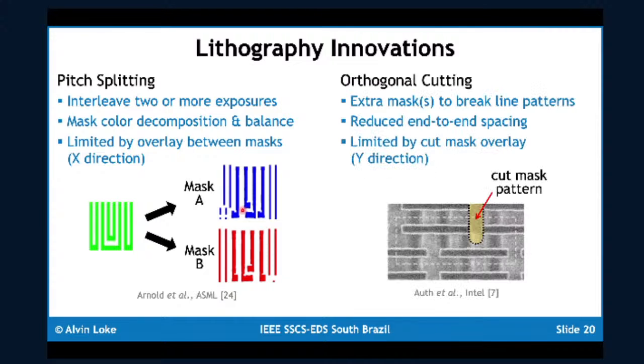Another approach is to use orthogonal cuts, which was introduced by Intel at the 45 nanometer node to reduce SRAM area. The idea here is that you print horizontal lines first and then use a cut mask to basically break the features. Why is this important? Because if you were to just print a line with a wavelength limited exposure, you end up with all sorts of essential near field diffraction artifacts, rounding at the ends, and also line pullback.